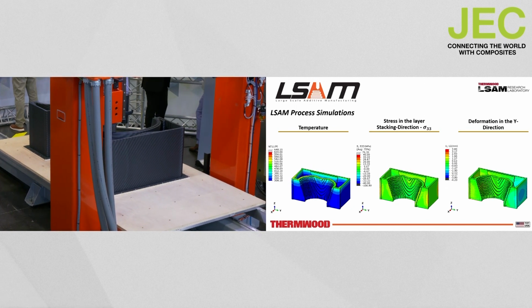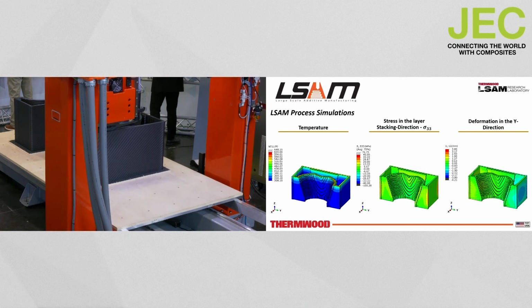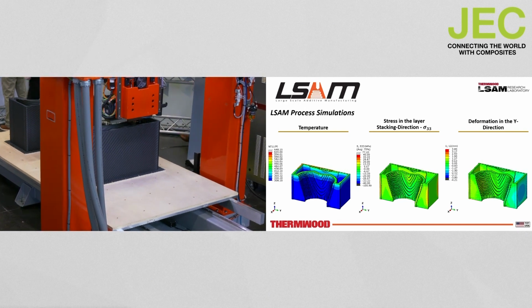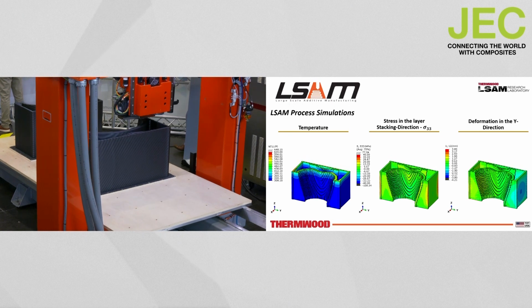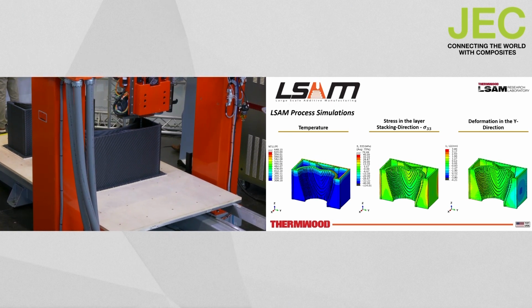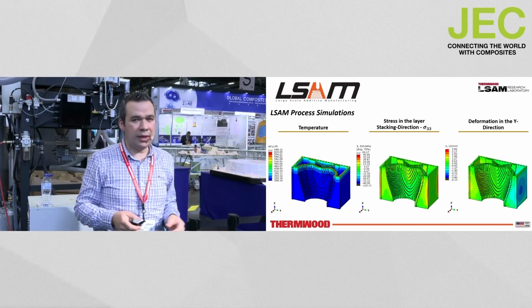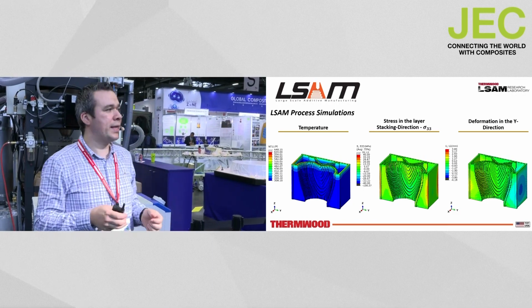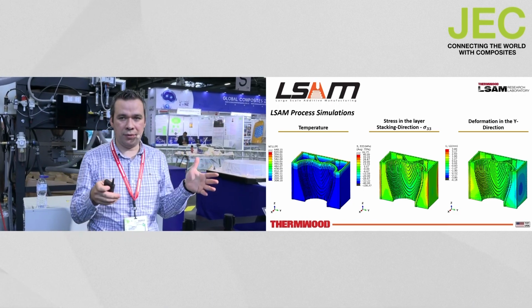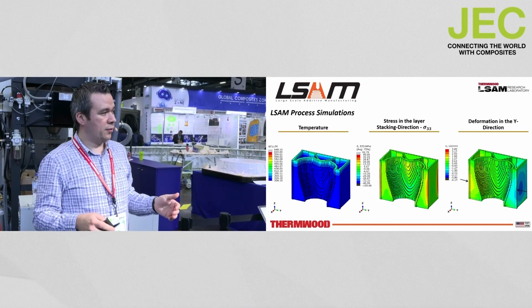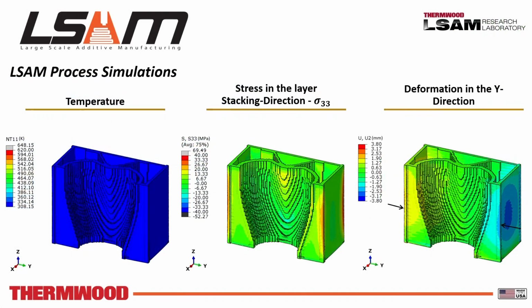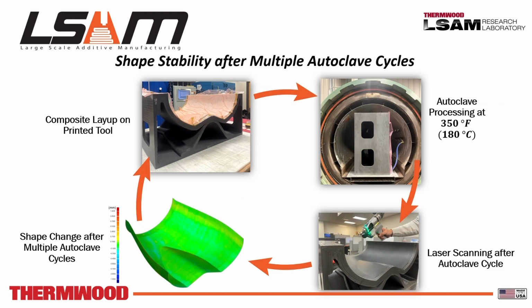In the middle, we're looking at the stresses in the layer stacking direction. Those are the stresses that will drive delamination when delamination is likely. In this case, it's not a problem. But then on the far right-hand side, we're looking at the deformation in the y direction. So you will notice that this tool actually springs in to some degree, and it's something we can predict and compensate for.